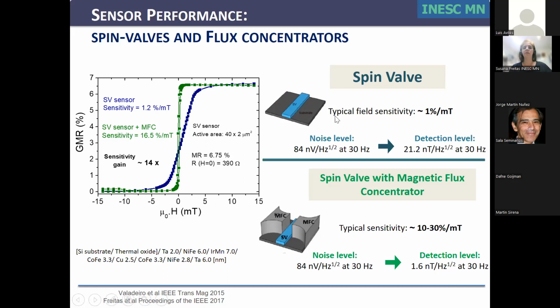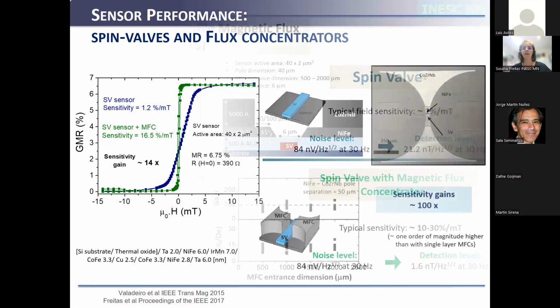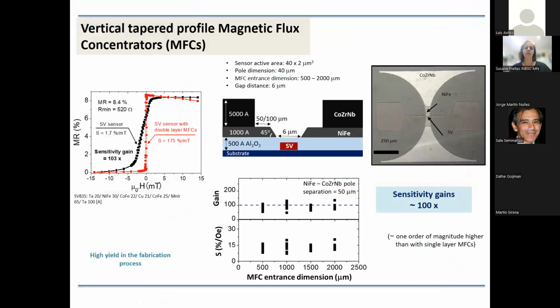And this is an example. If we have a simple spin valve or GMR sensor, the transfer curve will have this very nice linear response. As soon as you start to concentrate the magnetic field from outside, you have a really sharper sensitivity. So this is a very efficient way to focus the field, and we have done this for GMR and also for TMR. And one important parameter here is how to do this without occupying a lot of space. Because if you look, the sensor is here, these are the contacts laterally. But then if you want to add these extra magnetic flux concentrators, everything takes space. So your device is always doubling the size. The footprint is always increasing.